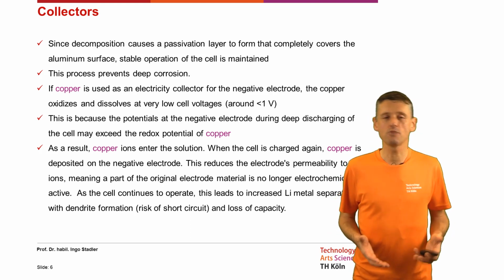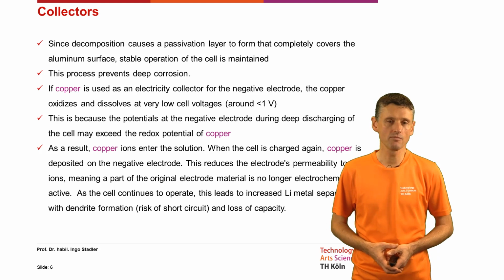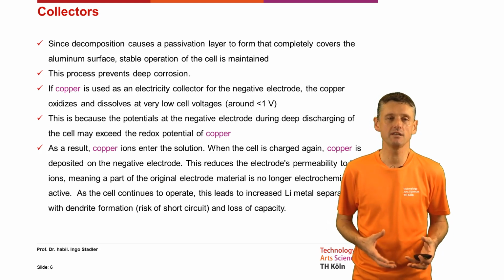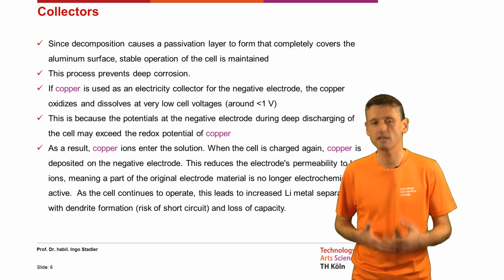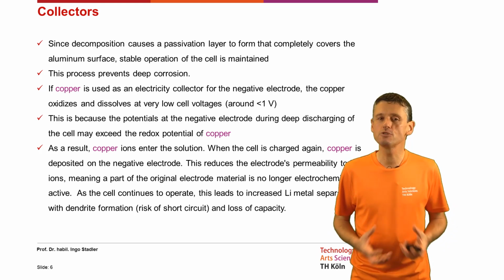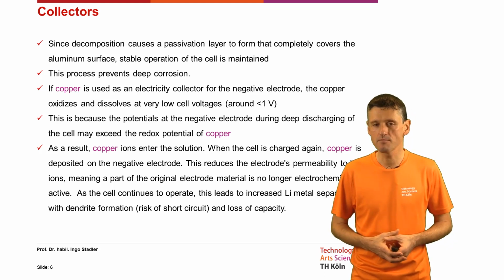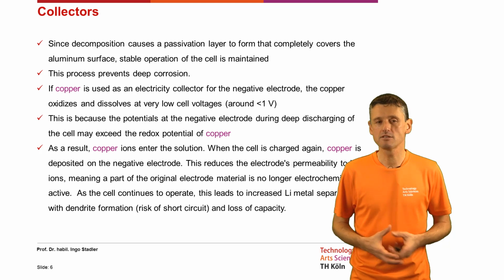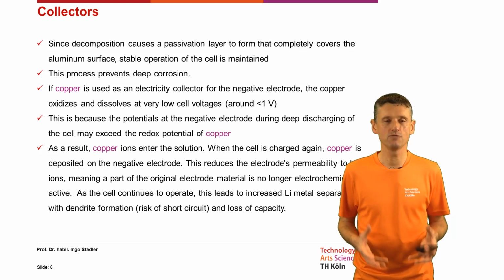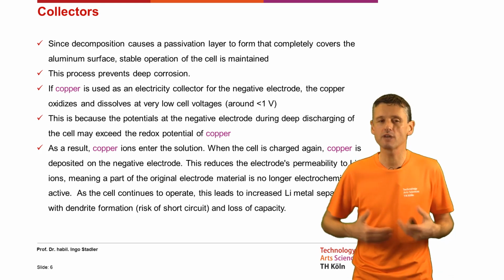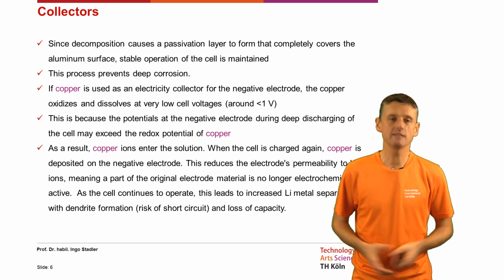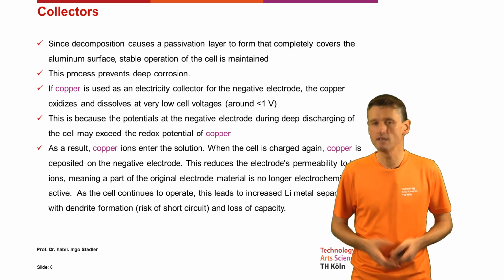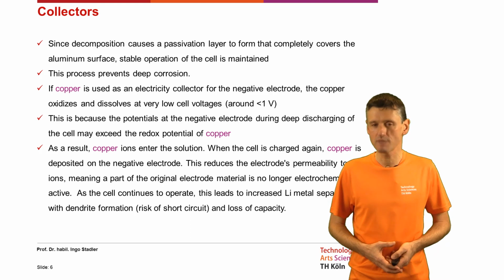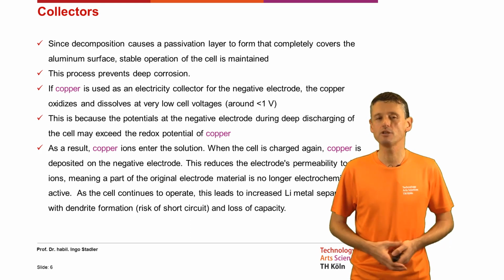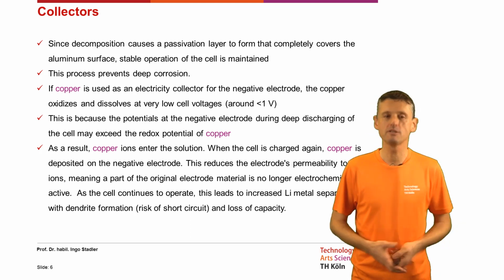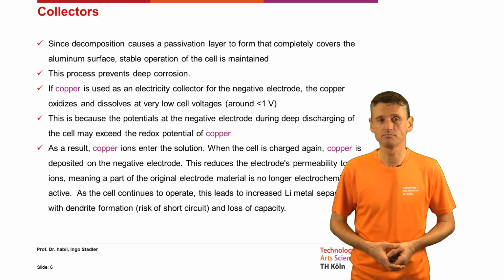As a result, copper ions enter the solution, and when the cell is charged again, copper is deposited on the negative electrode. This reduces the electrode's permeability to lithium ions, meaning a part of the original electrode material is no longer electrochemically active. As the cell continues to operate, this leads to increased lithium metal separation with dendrite formation, risk of short circuit and loss of capacity.